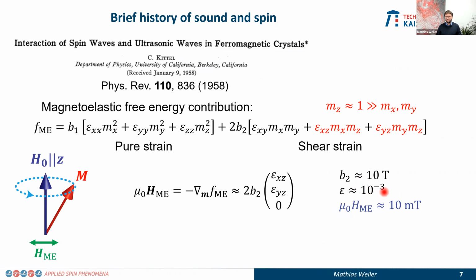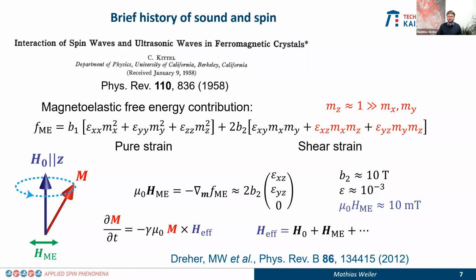And the strain in surface acoustic wave devices is typically on the order of 10 to the minus 3, and that gives a magnetoelastic field on the order of about 10 millitesla. So that's already very promising. One can then take this magnetoelastic field, insert it in the total effective field, and then solve the Landau-Lifshitz equation. And by that, one immediately sees that this will cause magnetization dynamics.